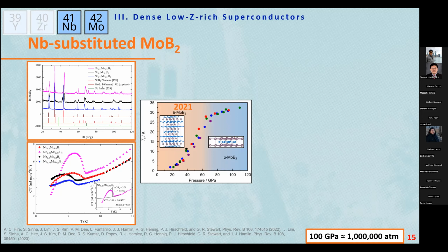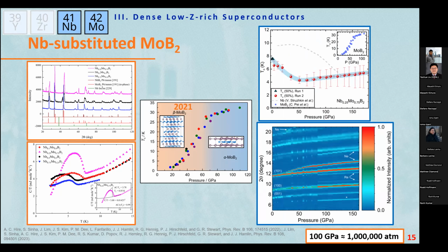And the next step is obvious: we squeeze this sample to see whether the superconductivity increases or not. But unfortunately, the pressure kills the superconductivity in the substitution study. Compared with the pure molybdenum diboride at 100 GPa, which has about 30 Kelvin of superconductivity, our case is around 5 Kelvin. So the niobium substitution suppresses superconductivity in molybdenum diboride. That's what we found. And we didn't have any structural transition in this substitution study.